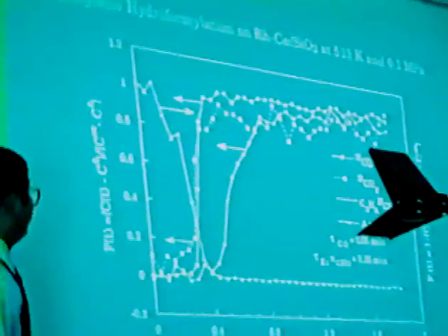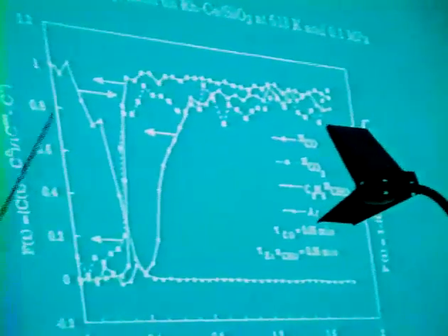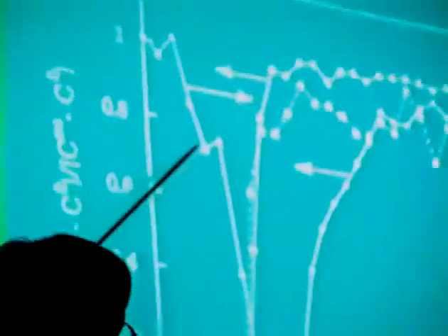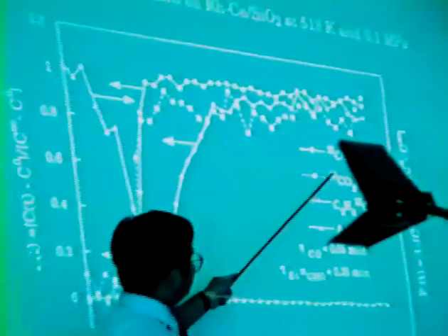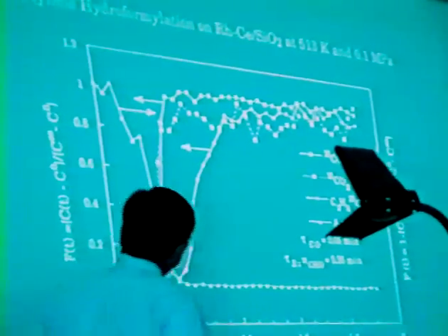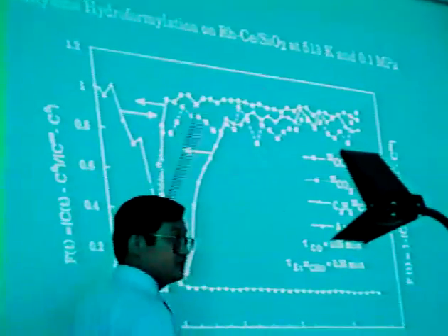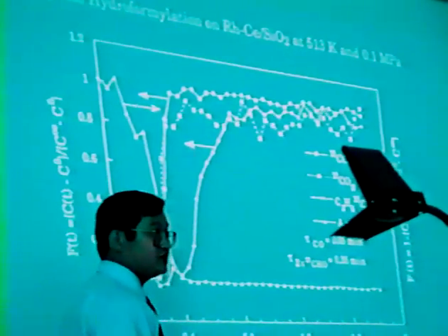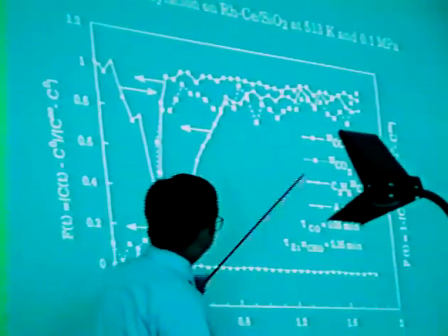And here is the gas phase response. Argon was added with the C12O to determine the effect of the flow patterns and the gas phase holdup on the response. So C12O is not shown in this figure here, and this is the response of C13O, and you can see the CO2, C13O2 follows the C12O very closely. So this indicates CO oxidation also takes place on the surface, which is a very fast reaction.